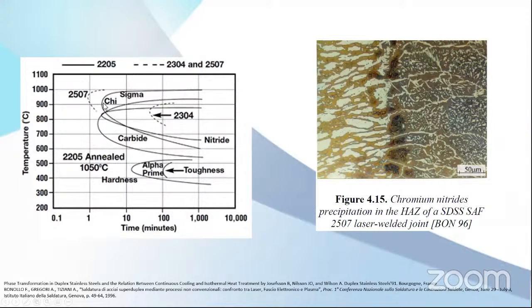So for duplex, for example, duplex material has a very high ferrite content, like 40 to 60% ferrite. So you have to cool it before reaching the nose. When you reach the nose, then you can get the secondary phase precipitation. The higher the alloy, the easier it is to get secondary phase precipitation. This is super duplex, very high alloy, so it's very fast. And this is lean duplex, lower alloy duplex, so you can have some time before the secondary phase precipitation.